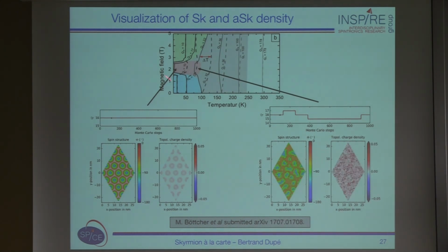On the left part, you are at very low temperature, which is around 1 Kelvin. You see that you are in a skyrmion lattice. It's a 4x4. As the time of the simulation goes on, you see that the topological charge stays absolutely located around these skyrmions here. And actually, there is not much going on. So you even have the impression that the movie is not running.